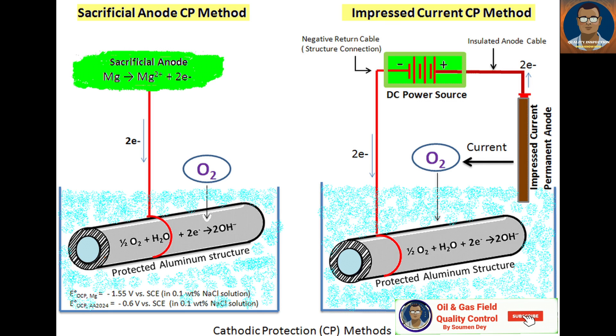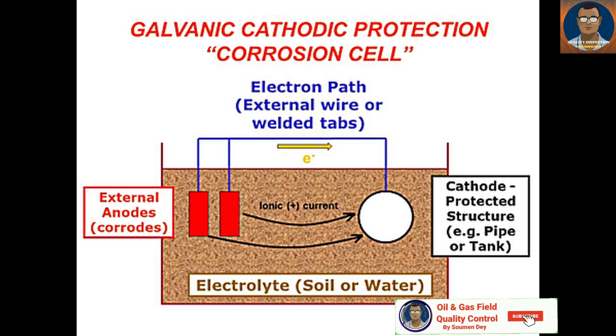The simple electrochemical circuit exists within the electrolyte — that is, in soil, seawater, river water, or pore water within concrete. DC flows off the corroding anodic areas and must complete the electrical circuit, so it flows through the electrolyte and discharges on the non-corroding cathodic areas. In the metallic circuit, current flows electronically by electron movement; in the electrolyte, it is via ionic movement, termed ionic conduction. The cathodic areas receiving current flow from the electrolyte do not corrode.